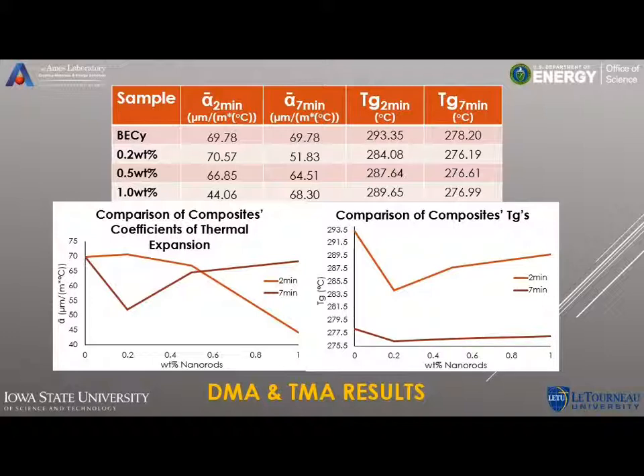Now, this marked difference between the low weight percent and the high weight percent occurs because when you get a high weight percent of filler material added to a polymer composite, the filler material tends to aggregate in clumps, and so it functions less effectually as a composite material. And so we would expect that the low weight percent composites show better properties, as we were indeed seeing.